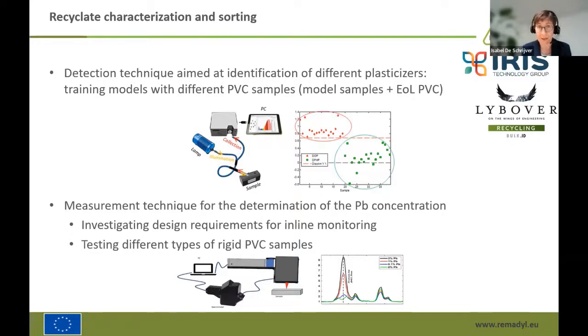The second measuring technique that we are developing is to detect the lead concentration, because lead, if you detect it, it's one aspect, but also to have an idea about the concentrations of lead being used in the materials. And there we are trying to build an inline monitoring line at the recycling plant, and we are testing different types of rigid PVC samples to be able to detect the high amounts of lead and to make sure that we are well below the REACH legislation limit that are being set up for those different materials. So that's, of course, the first step.